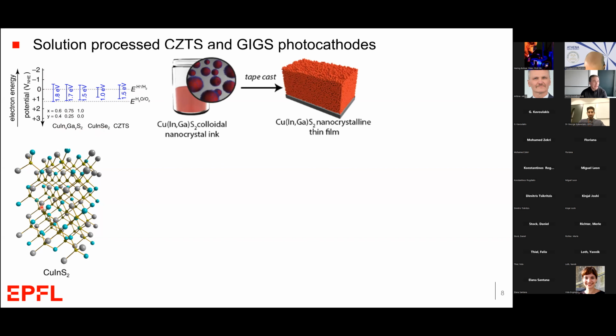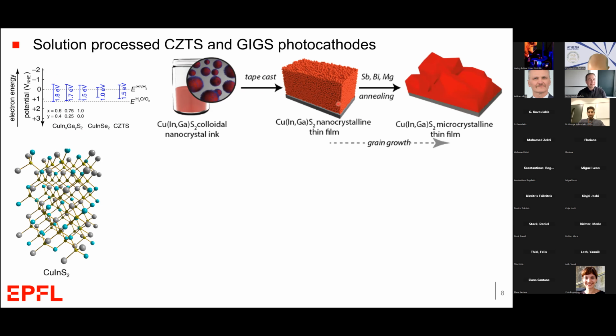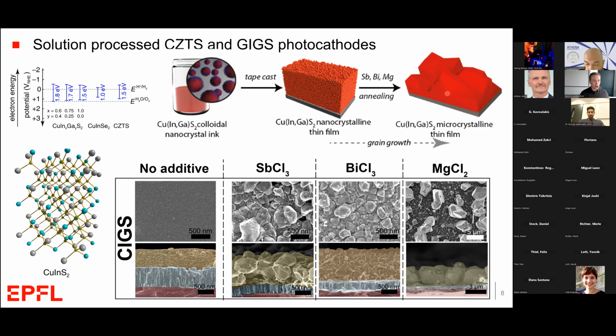Moreover, these types of materials can be made by a simple colloidal formation of nanoparticles and then casting them into thin film electrodes. Unfortunately, when we do this, the electrodes don't work very well, and we had to develop a type of eutectic salt annealing to crystallize the nanoparticles here into large crystal domains to avoid, of course, recombination at grain boundaries and improve the performance. The interesting thing is that we're able to find conditions to perform this sintering reaction at relatively low temperatures using these additives based on these chlorides.